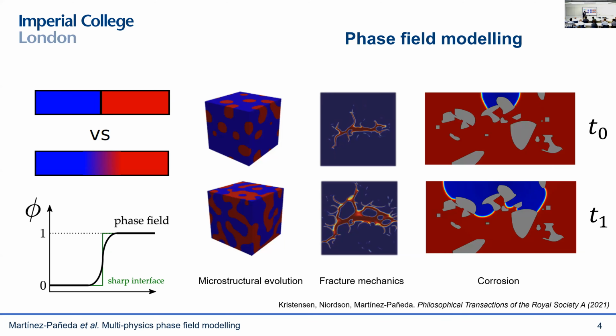I think it is the most popular computational fracture mechanics tool these days. You can see here that you can capture very complex fracture phenomena: nucleation of secondary cracks, crack branching, coalescence of multiple cracks. And we have also recently shown that it can be used for corrosion. So we can use phase field to describe how the corrosion front evolves, so the interface between the electrolyte, like seawater, and the metal, and how this changes.